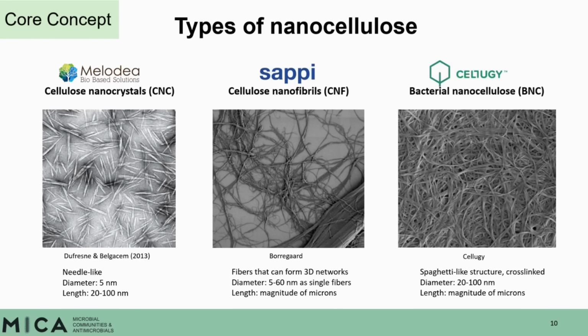CNC, which stands for cellulose nanocrystals, are the least fibrillated among the three. They're rigid, needle-like particles with a diameter of about 5 nanometers and length between 20 and 100 nanometers. We receive CNC from our partner Melodea, which is the second largest CNC producer worldwide. Then we have CNF, which stands for cellulose nanofibrils, which are more fibrillated than CNCs. They form flexible fibers and can create 3D networks. Their diameter ranges from 5 to 60 nanometers, and we receive them from our partner Sappi.